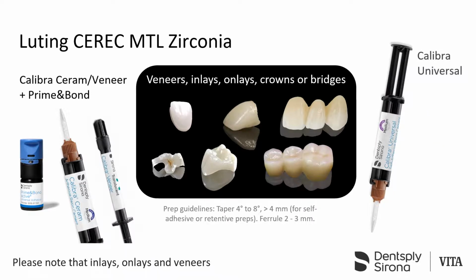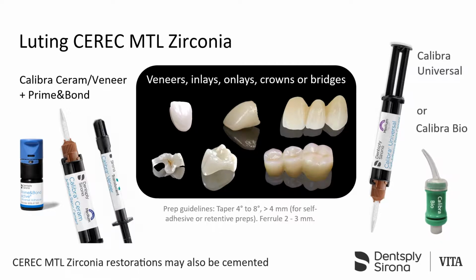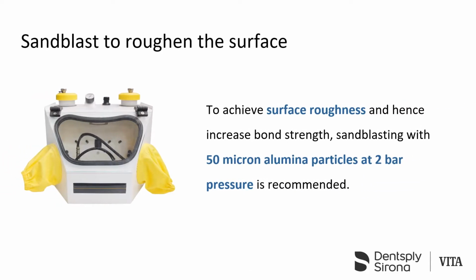Please note that inlays, onlays, and veneers must be luted in full adhesive fashion. Except for inlays and onlays, CEREC MTL Zirconia restorations may be cemented with Calibra Bio from Dentsply Sirona. For further details regarding cementation, please see the instructions for use of respective products. Hydrofluoric acid is generally not effective in creating surface roughness on zirconium oxide intaglio restoration surfaces. To achieve surface roughness and hence increase bond strength, sandblasting with 50 micron alumina particles at 2 bar pressure is recommended.